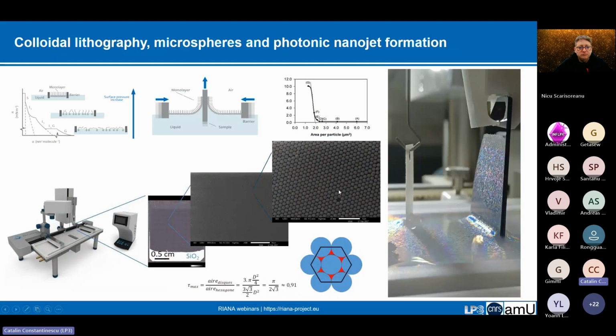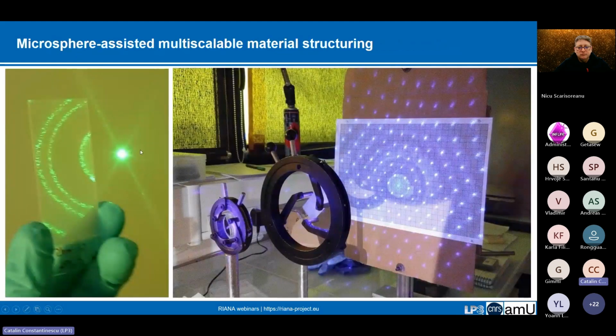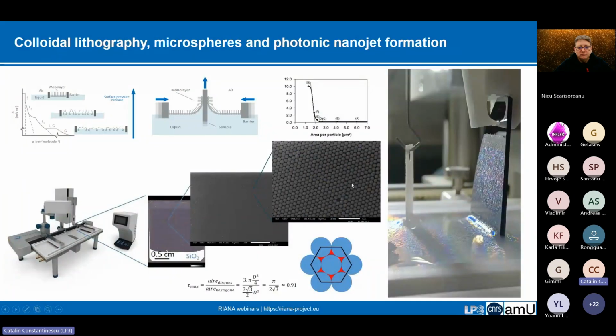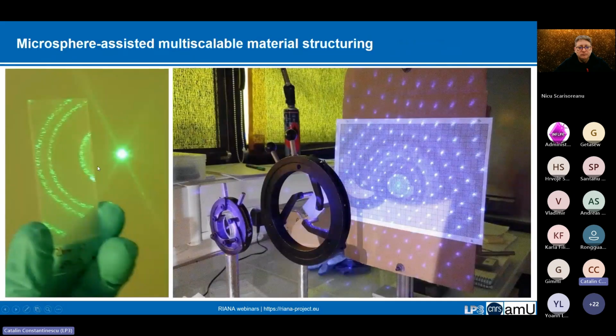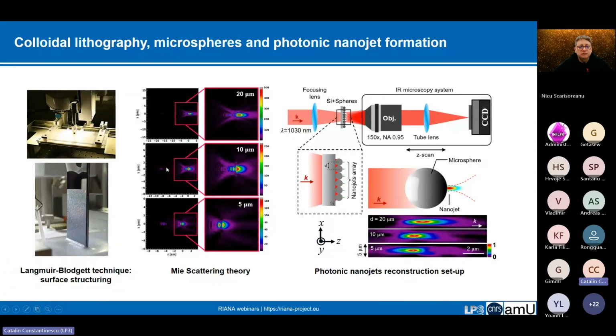So this concept can be extended further. It's easy to produce these monolayers of spheres. We produce them at the interface between water and air in a modified Langmuir-Blodgett setup, and then we can collect these spheres on a choice substrate. And since they are highly oriented in 2D single layer, we can use them as 2D materials, so they actually diffract. So we can see here a diffraction pattern. This was just for the fun of it. And by combining the laser parameters and microsphere size, we can achieve multi-scale patterning in a single process.